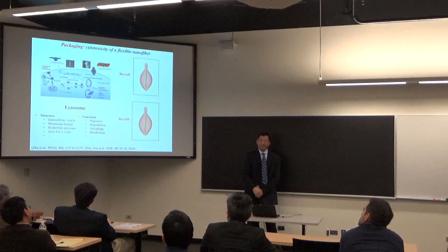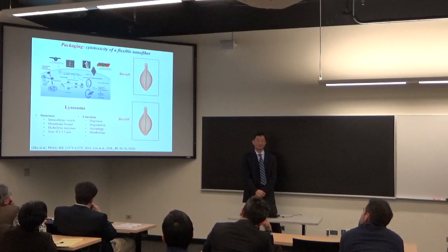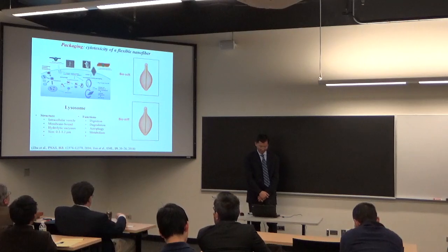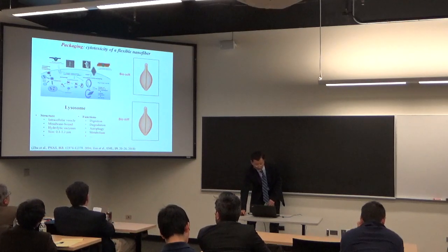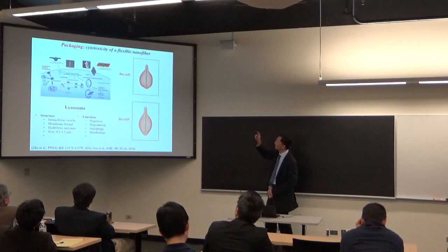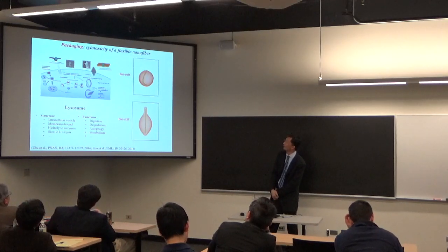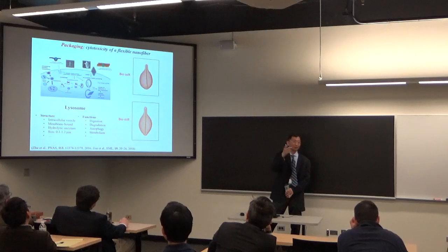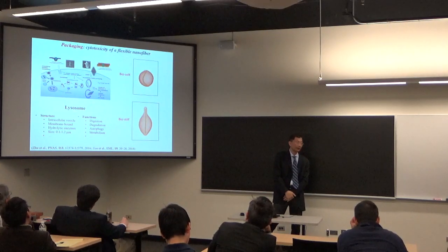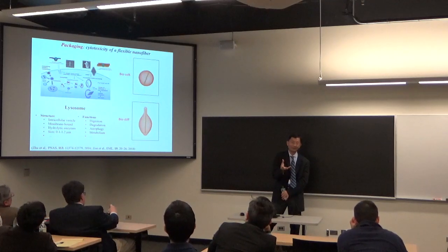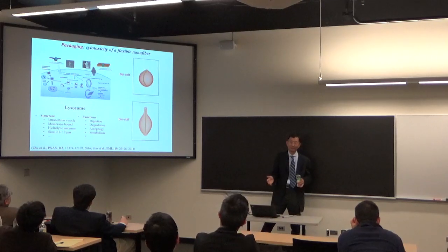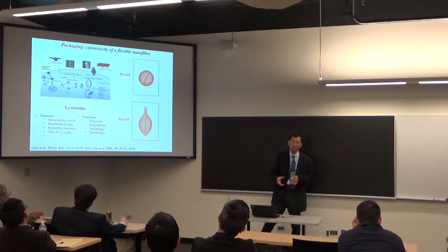Okay, so we ask a question, right? When biology interacts with materials, people think some materials are stiff, some materials are soft. Right? So what is bio-stiff? What is bio-soft? So we studied this problem. We find the definition of bio-stiff and bio-soft for a fiber can be defined the following way. Okay, if I have a long fiber packaged in a lysosome, because it's trying to protrude in there, there are two pinch forces, two compressive forces at the end. If the fiber buckles and coils within the lysosome, then we define that material as bio-soft, okay, because it doesn't fight against nature, because the lysosome is trying to package this material. If it is soft enough, it will coil around, it will yield to the biological confinement.